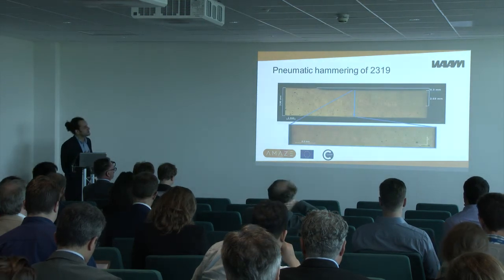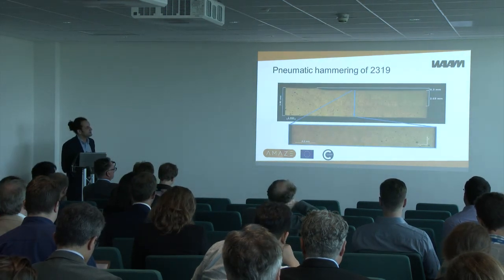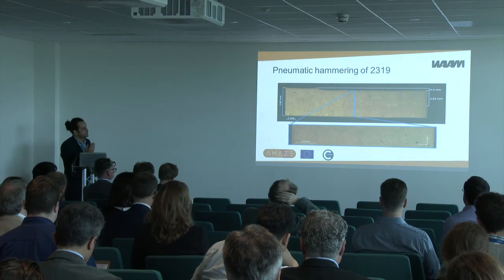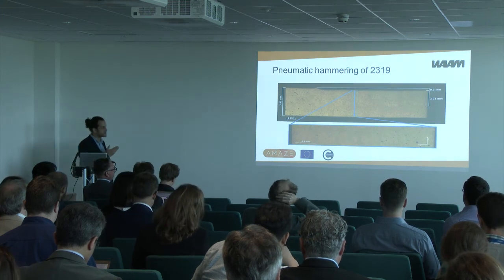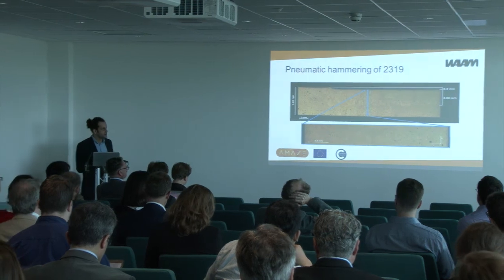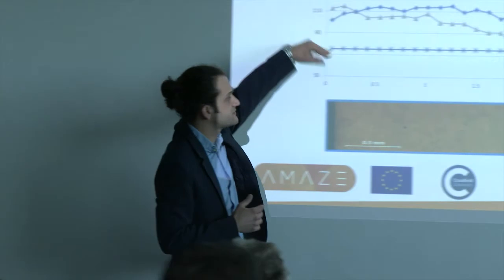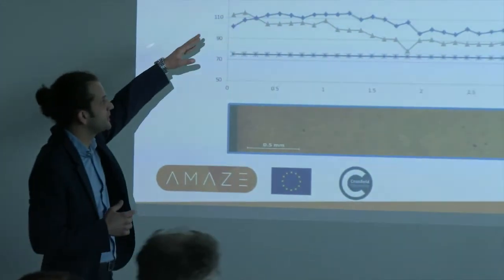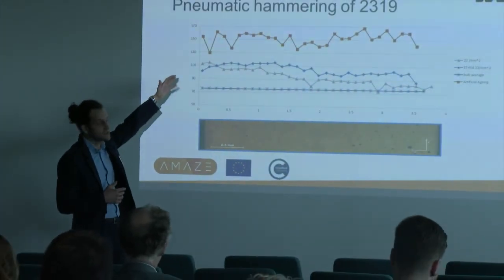Then we did the same treatment to 2319, and it's striking how much porosity has disappeared thanks to this process. Now the question is, we don't know whether the porosity has just been squashed or actually the hydrogen is in solution in this case. Nevertheless, the effect is evident and promising. And as you can see, with the addition of the pneumatic hammer treatment, we can improve the hardness substantially. And then with artificial aging, it goes up even further, as you would expect.